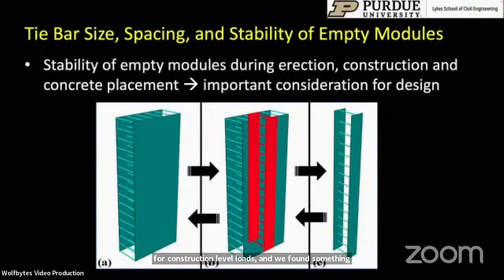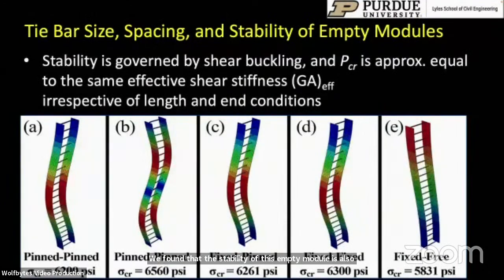And then we started looking at the stability of this empty module for construction level loads, and we found something fascinating. We found that the stability of this empty module is also fully governed by that same effective shear stiffness. This stability was found to be governed by shear buckling, and P critical for these empty modules was equal to GA effective, irrespective of the length and the end conditions. I still remember when we came up with this finding, I couldn't believe it for a moment, and I had to go back to all the theory and discover what was going on. And then I called Ron and I said, Ron, I think there's something interesting going on with this system. And we were able to understand the stability of this empty module and how it was independent of length, independent of boundary conditions, and governed solely by the shear stiffness of an individual unit that was part of the system.